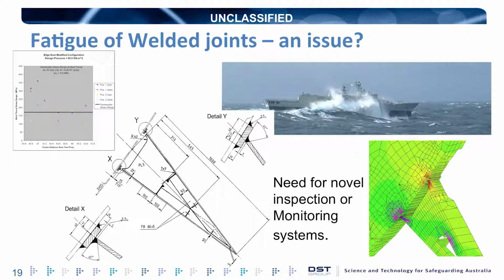The modifications were designed for the loads that we came up with. But the critical failure locations have now changed from the outside of the bilge keel to a position that's way inside of the bilge keel. But now I've got no way of telling whether they're cracking or not. So what NDI techniques can I use? Is there any coating I can put on the welds at the beginning of the day to give me an indication that through the life of the ship I'm experiencing some failure there?